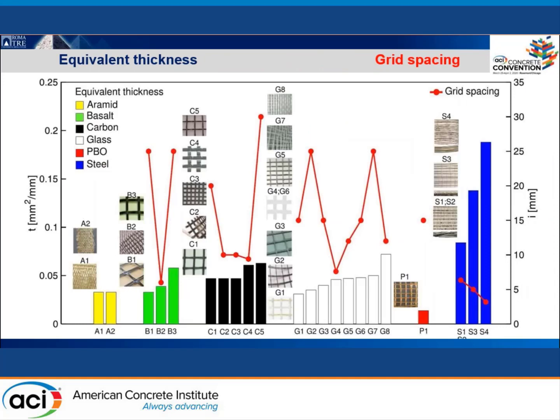The systems, as you can see in this slide, are classified based on the textile that is used. So we have aramid, basalt, carbon, glass, PBO, and steel textile. The equivalent thickness of these systems ranges from 0.04 millimeters up to 0.22 millimeters, while the grid or fabric spacing ranges from 5 millimeters to 30 millimeters. So you can see here the number of different textiles and also the differences in thickness and spacing of these systems.